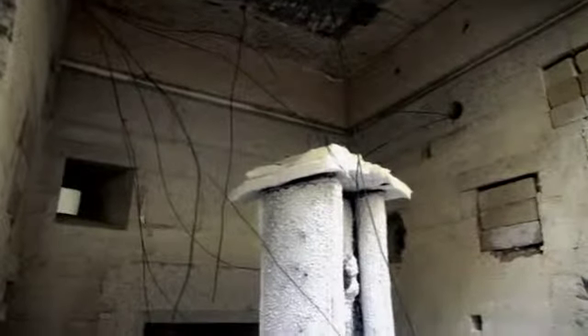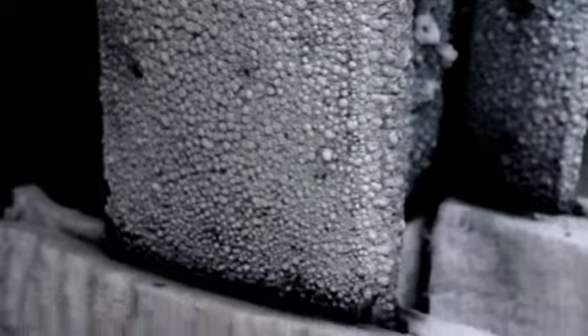These materials expand up to 50 times its original thickness to produce a very large, soft, lightweight char to protect the steel from the heat of the fire. Now, without this intumescent, the steel can reach the critical failure temperature that will lead to structural collapse after around 10 minutes. Once intumescent coating is applied, this structural failure temperature can be extended for anything up to 4 hours.